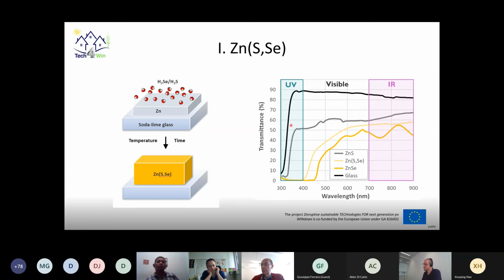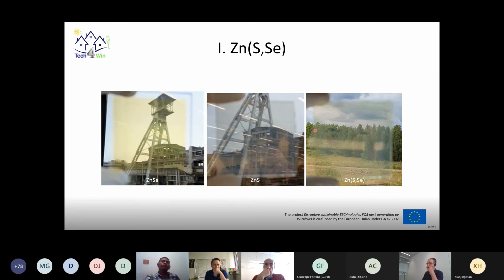That's what you also see in these curves. You see the glass reference. You see indeed that the zinc selenide has the lowest band gap. You see indeed that the zinc sulfide has a higher band gap, and you see that we're somewhere in between. Absorbing very well the UV parts, leaving through as much as possible visible and also infrared. For the moment, the thickness of material we are optimizing is around 1 micron, so still quite thick because of device optimization reasons. Of course, we will have to reduce that thickness later on to become even more transparent. But it's already quite transparent, which you can see here.